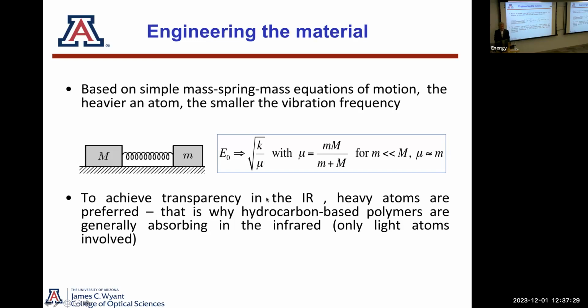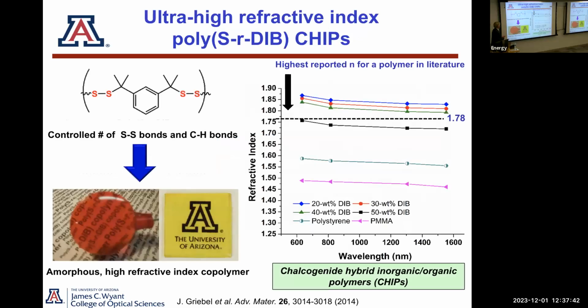That's why anything with hydrogen in it, we saw that water peak in the fiber spectrum, has absorption in the infrared. So we started working on these materials about 10 years ago. It's interesting that I just changed this picture of the structure this morning, because we'd worked on the materials for a number of years before it was made evident that the initial structure that was determined was wrong. It was reactive, but where the sulfur was reacting with the polymer part was different than what was initially thought. But now we have the right structure.